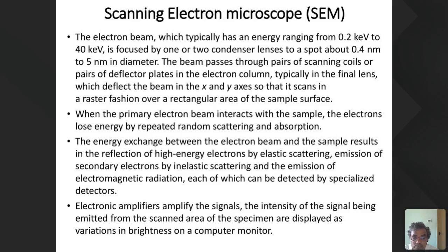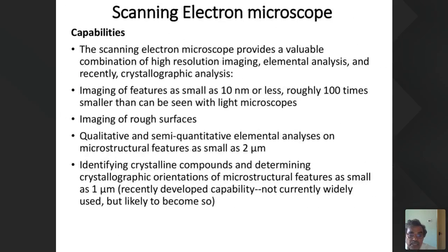The primary electron beam interacts with the sample. The electrons lose some energy by repeated random scattering and absorption. The energy exchange between the electron beam and the sample results in the reflection of high energy electrons by elastic scattering, the emission of secondary electrons by inelastic scattering, and the emission of electromagnetic radiation. Each of these can be detected by suitable detectors, such as the secondary electron detectors. These detector signals are amplified and the intensity of the signals is displayed as brightness on the computer monitor as a digital image. This will be used for studying the topography or the structural characteristics.